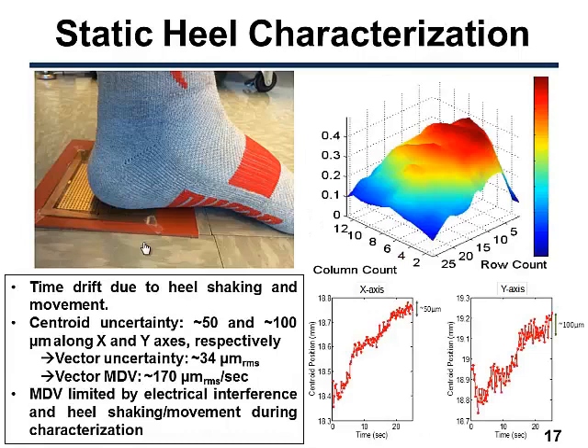Finally, we tested the ground reaction sensor array underneath a static heel. The top right figure shows the output voltage profile when we step on top of this ground reaction sensor array. With this output voltage profile, we can calculate the centroid's position along the x-axis and the y-axis over these 20 seconds. And the time drift is due to shaking and movements during the measurement. To simplify, we can get a minimum vector velocity resolution of 170 micrometer per second. The increased MDV is due to heel shaking and movement during the measurement.